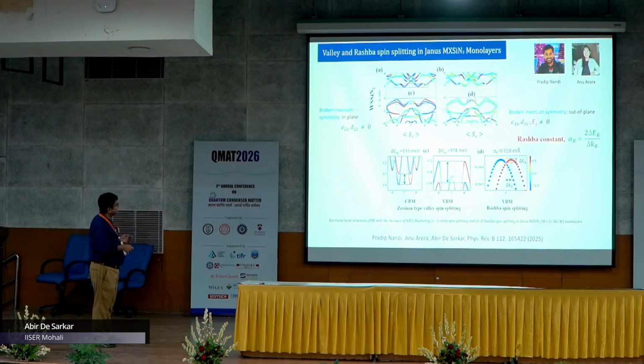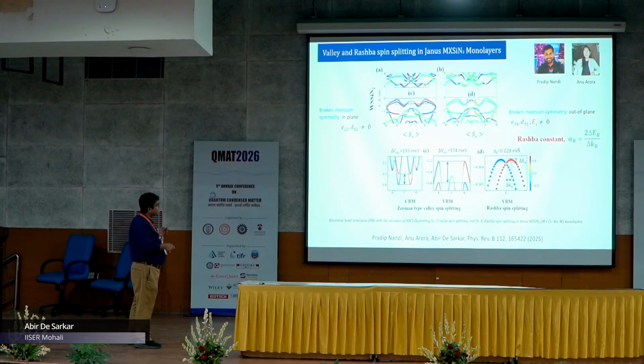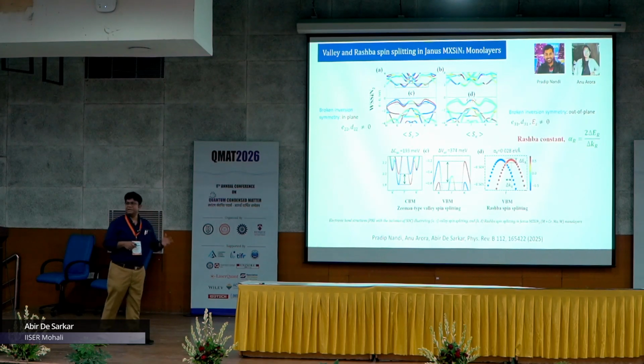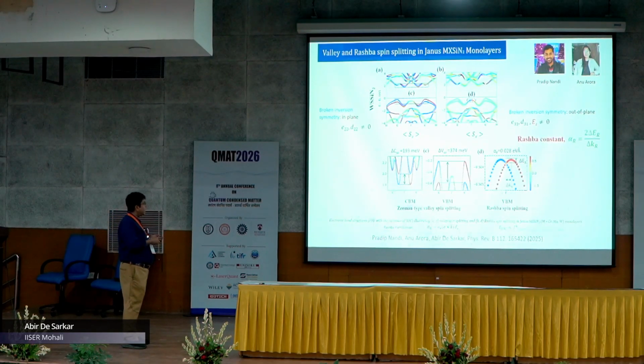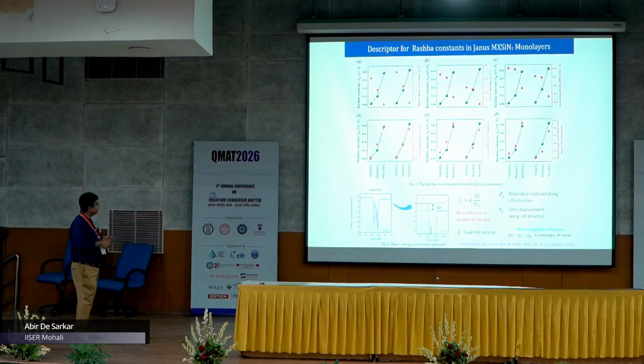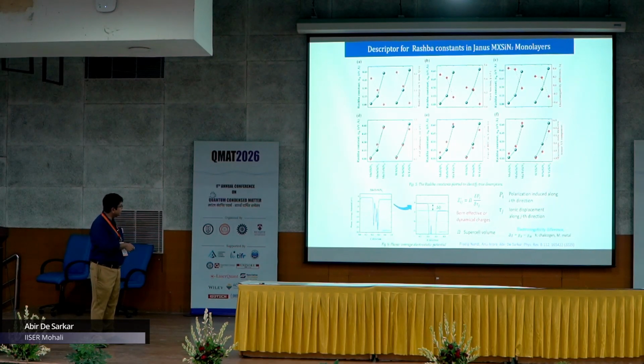And since the inversion symmetry is also broken along the z direction, an out of plane electric field arises in it intrinsically, and that together with the spin orbit coupling brings about this momentum dependent spin splitting, or the Rashba spin splitting, which is quantified by this Rashba constant. So, it also shows a Rashba type spin splitting. And then we proceeded to find the appropriate descriptors for this Rashba constant, and the Rashba constant is found to be proportional to the difference in the electrostatic potential between the edges of these two-dimensional monolayers.